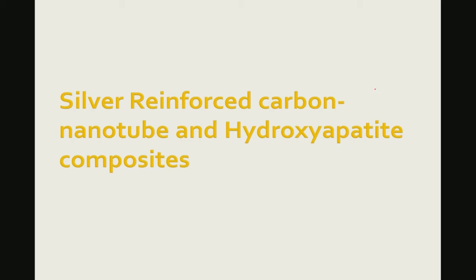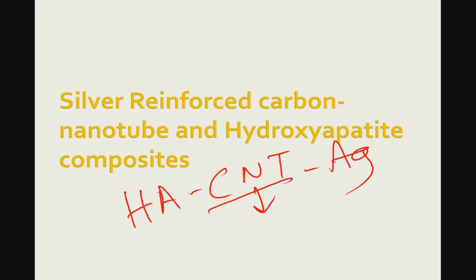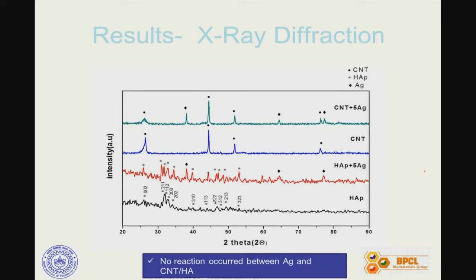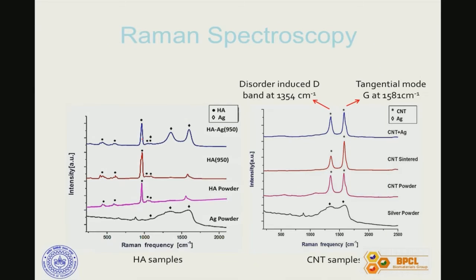In the next few minutes I will show results related to hydroxyapatite-carbon nanotube-silver composites. Carbon nanotube can be either single-wall or multi-wall, and both morphologies can be present in the matrix. For these hydroxyapatite-CNT-silver composites, classical X-ray diffraction analysis confirms that high characteristic hydroxyapatite peaks are retained in the spark plasma sintered composites. Raman spectroscopy shows the disordered (D) peak and graphitic (G) peak clearly present at two distinct Raman bands of 1354 and 1581 cm⁻¹ respectively.